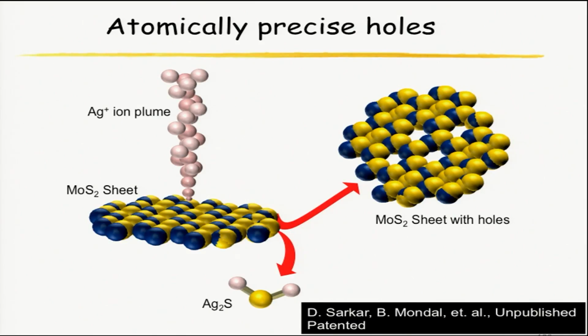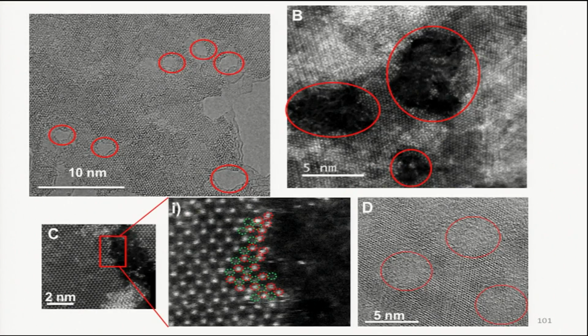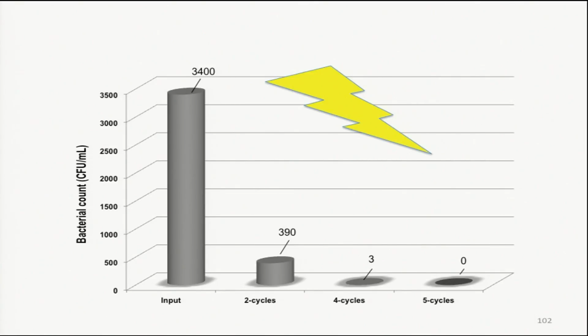So this is also very interesting. What's the new direction? We are looking at one-atomic-layer membranes of this kind, selectively drilling holes in these membranes. This is molybdenum sulfide. When you drill holes selectively, you can create holes in such a way that only molybdenum is there in these holes. And people in this audience have really shown that such membranes, if you create holes by our process, these are atom-specific microscopy, which proves that this is molybdenum, molybdenum, molybdenum. These are actually sulfurs in between. So this is a molybdenum-rich surface, and with such molybdenum-rich surfaces, you can use white light and produce hydrogen peroxide, and with hydrogen peroxide, you can destroy bacteria in no time. Very interesting new kind of materials, new disinfection is possible.